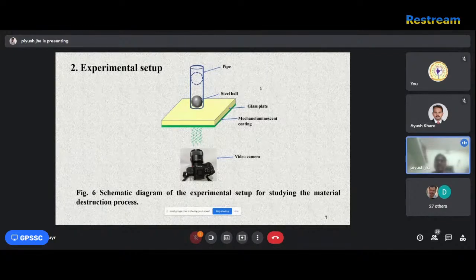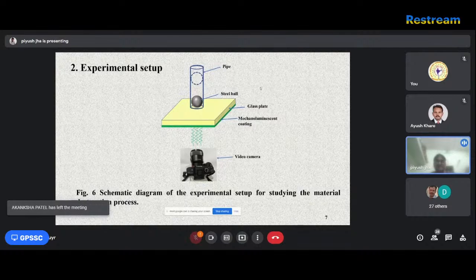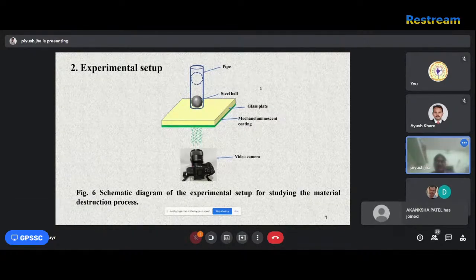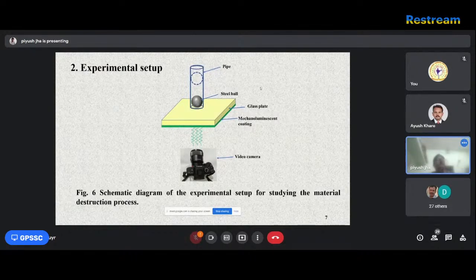For the damage generation and its behavior, there have been some reports which are limited to the damage assessment before and after static and dynamic stress analysis. If the damage generation and its behavior can be visualized during the mechanical testing, it can contribute to enhancing the performance and ensuring the reliability of the product. Therefore, an in-situ evaluation technique which can provide a dynamic stress-strain distribution and track fracture phenomena has been strongly demanded.